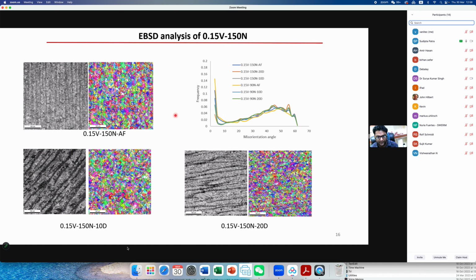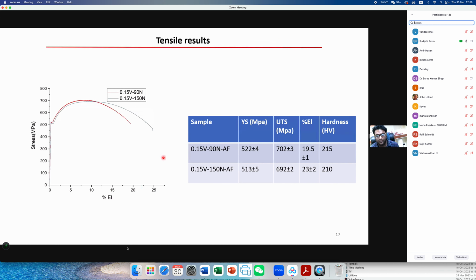From the microstructure study, we could do only two tensile tests in the two different chemistries, 90N and 150N, in the as-forged condition only. We could not do the normalized condition. Samples are under preparation. So here we observe 522 yield strength and 513 yield strength in case of 90 nitrogen and 150 nitrogen, with UTS in this range, and elongation around 20%, and this is the hardness value.